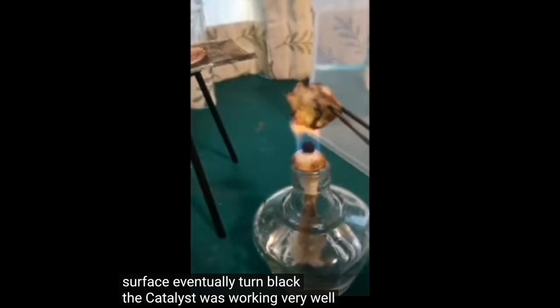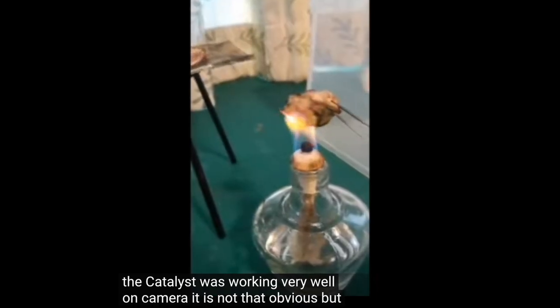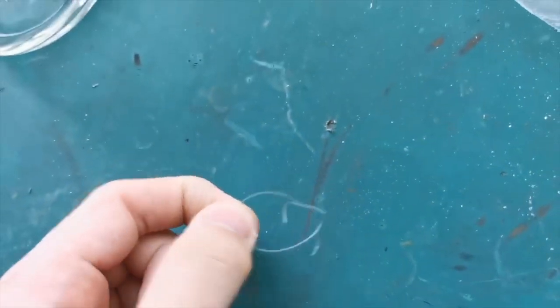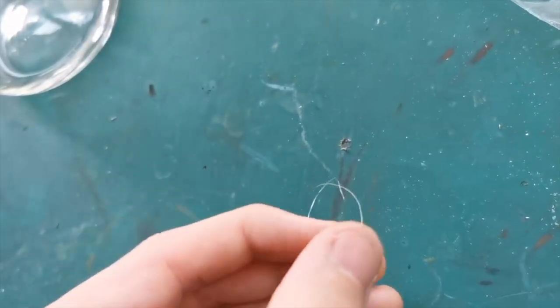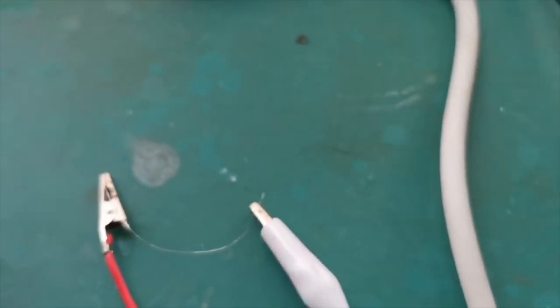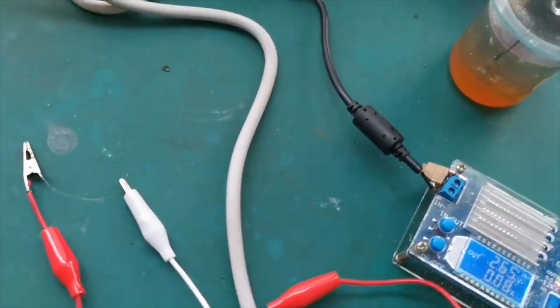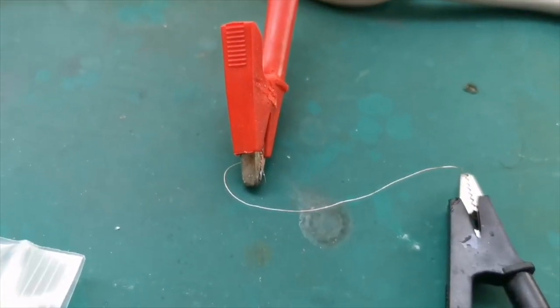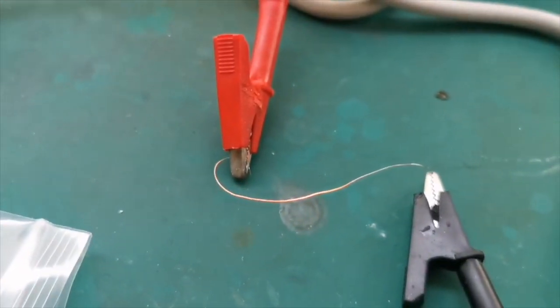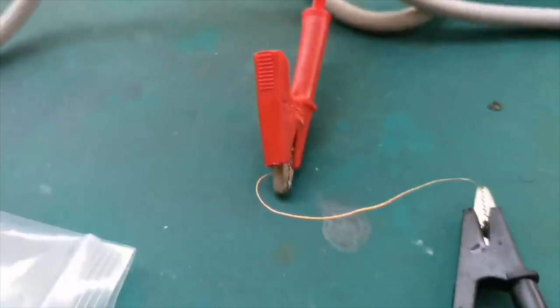Industrial productions use platinum wires or platinum fused in substrates such as zeolite. I made some platinum fused quartz wool in a previous video, but it wasn't very successful. So instead, I gave a try on platinum wires. Here is a piece of 10 centimeter by 0.1 millimeter platinum wire. I connected the wire to two alligator clips and set my limiting current to 0.08 amps. It is very important to set a limiting current and go up slowly, or else the wire may melt.